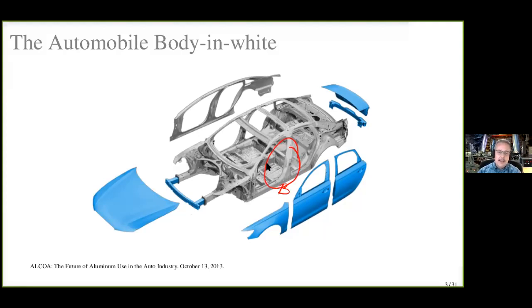So if we can get this to be fabricated from a high strength aluminum alloy, it opens up a potential for a lot of mass savings. But even more than that, it opens up the potential to begin forming some other body components nearby that attach to the B pillar out of aluminum.